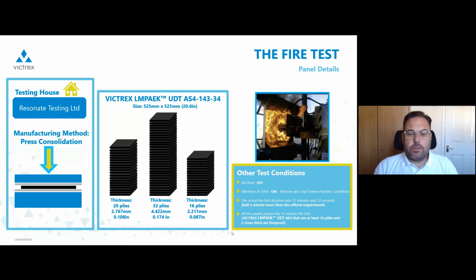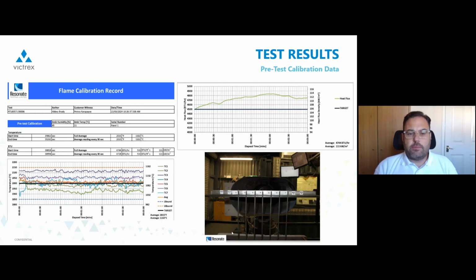So we tested all these 3 panels, and I'm happy to say that everything passed. Yes. Even the thinnest panel, which was just over 2.2 millimeters thick, passed the requirement, meaning that after 15 minutes there was no fire penetration. So again, we dive a little bit into the details of the tests.